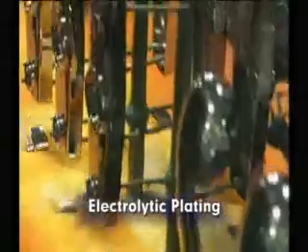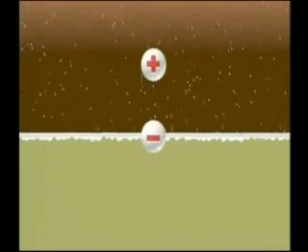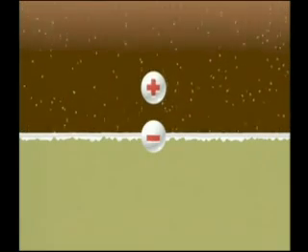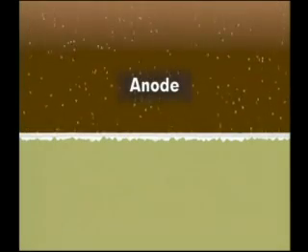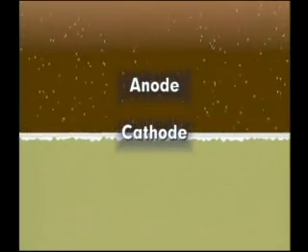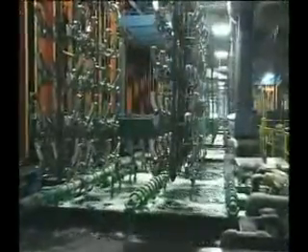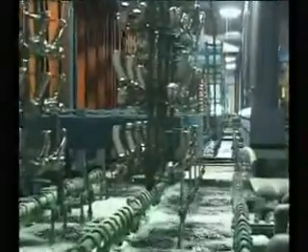Electroless plating provides a dull metallic finish and is often applied to plastic products used in shielding applications. But electroless plating is also the first phase in the electrolytic plating process, which provides a decorative bright chrome finish. Electrolytic plating uses electrical current to draw or precipitate positively charged plating metals out of solution to coat the negatively charged conductive plastic part's surface. The positively charged plating metals are referred to as the anode, and the negatively charged plastic part, the cathode. To arrive at the final chrome-plated finish, plastic parts must go through a minimum of 12 preparation, plating solution, and rinse baths. The various plating solution baths include a bright copper plating bath, a bright nickel plating bath, and the final chrome plating bath.